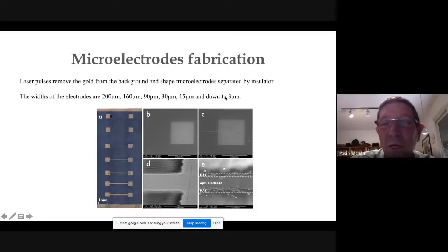And we can go down to 3-micron lines. You can see this is a 3-micron electrode. This area here is called the HAZ, heat-affected zone. I told you there is no heating, but there is a little bit of heating. This heat-affected zone is about 1 micron, so we can make 3-micron electrodes. Usually we don't need such electrodes. Most of the devices are 90 or 160 microns.